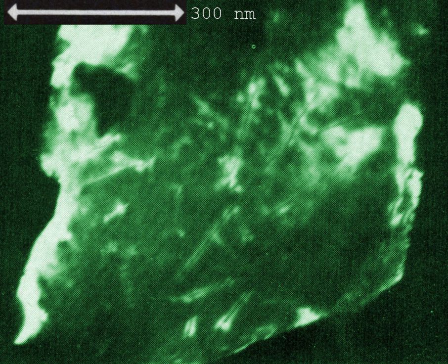The resulting shape depends on the type of material, the concentration of the etchant, and the temperature of the etch bath. In crystals and glasses, selective etching is due to the reduced density of the ion track. In polymers, selective etching is due to polymer fragmentation in the ion track core. The core zone is surrounded by a track halo in which cross-linking can impede track etching. After removal of the cross-linked track halo, the track radius grows linearly in time. The result of selective etching is a trough, pore, or channel.